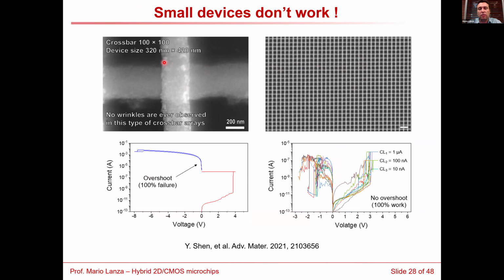So we fabricated, with electron beam lithography, 320 by 420 nanometer devices in an array of 100 by 100 wires. So this is like a 10 kilobit array. And we tested, here you see only one part of the array because the array is big. And then we tested the devices again with the same protocol.